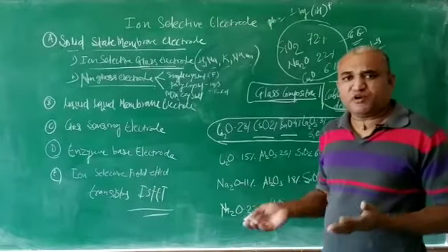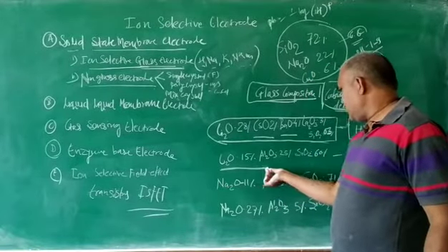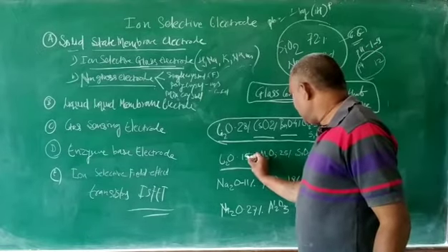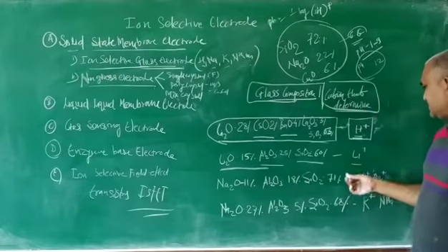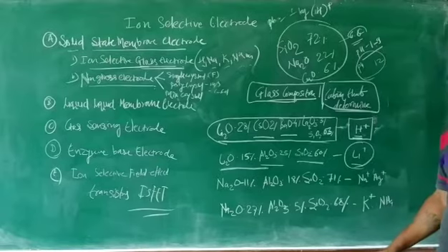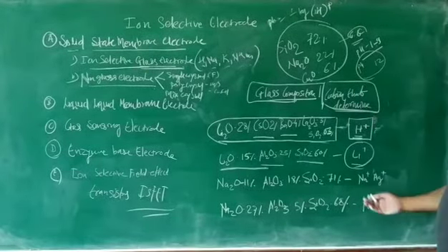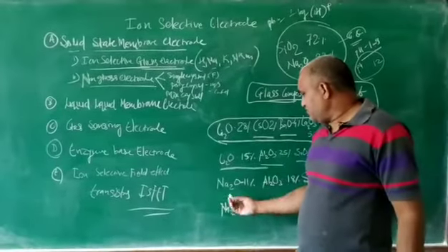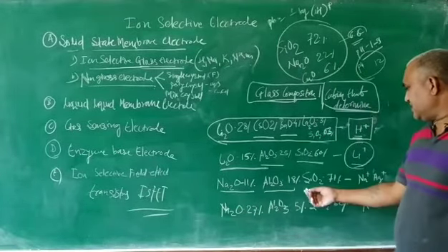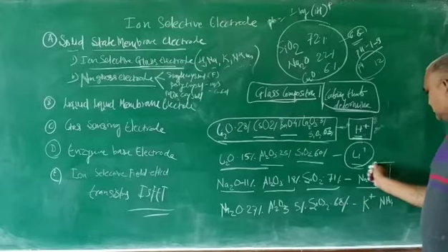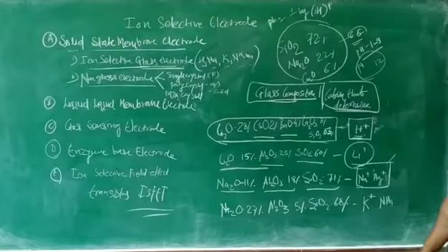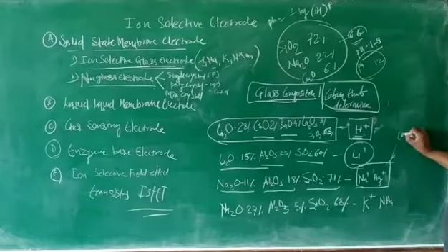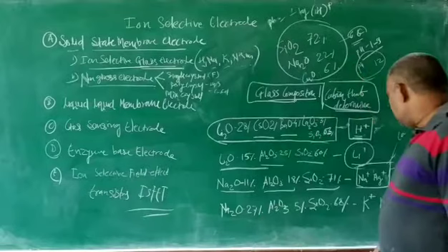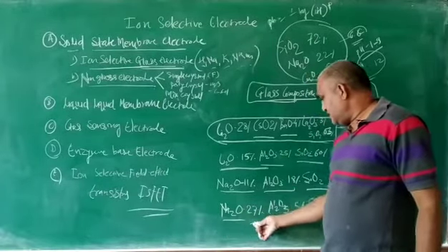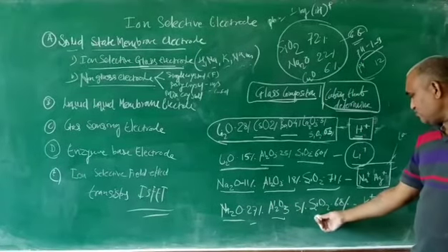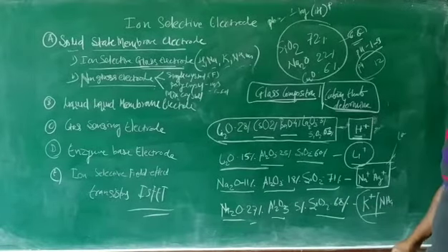So for checking lithium, we use this type of percentage. Here lithium 15%, Al2O3 25%, SiO2 60% for lithium ion concentration. For sodium and silver ion concentration, we use Na2O 11%, Al2O3 18%, SiO2 71%. With this we detect the sodium and Ag ions in the given solution, or we detect the concentration as well as the activity of the solutions. For detecting potassium ions, we use Na2O 27%, Al2O3 5%, SiO2 68%.